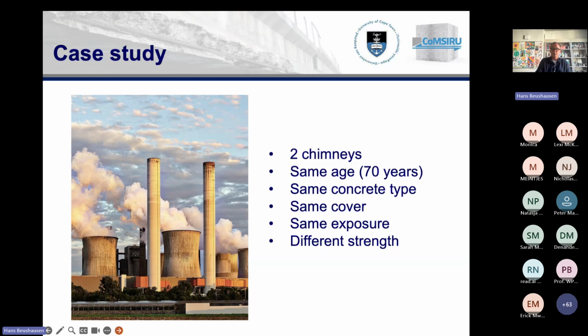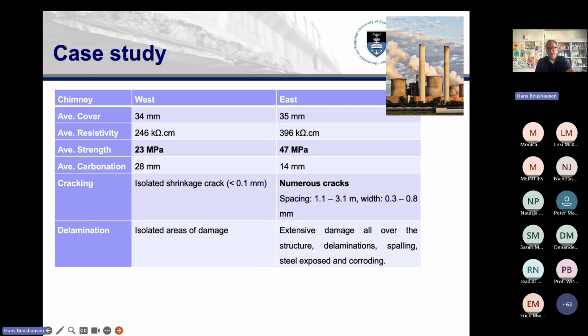And to give you one example of what this means for the performance of structures, here we looked at a power plant in South Africa, which had two chimneys. It was built about 70 years ago. Both chimneys had the same age, the same concrete type, which we tested chemically, the same cover, the same exposure, but they had different strength. Maybe they, by accident, made the one chimney not as strong as they should have. And looking at the performance that we measured on that structure, so we're looking at the west and east chimney, you can see they had the same cover depth of around 35 millimeters, which is not too bad.